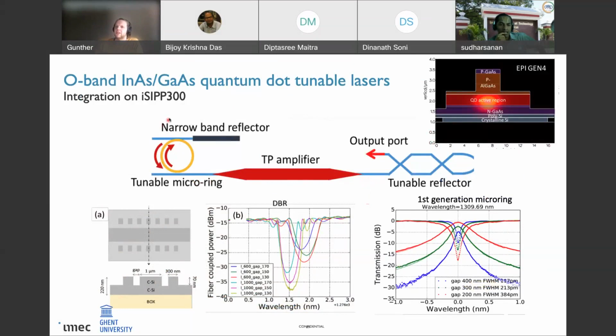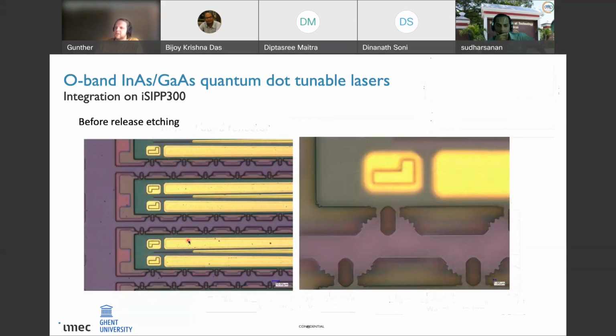This is done on a 300 millimeter silicon photonics platform. So we can pattern these first order gratings using immersion lithography on 300 millimeter silicon wafer. And now we are working on developing the gallium arsenide process and the release process to transfer print these components. So that's work in progress at the moment.